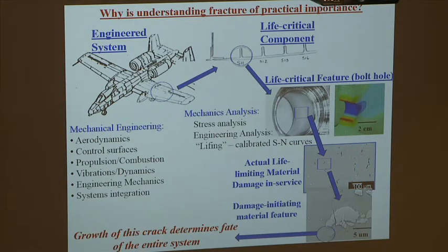And if you really zoom in and see what these cracks look like, they tend to initiate at small particles and grow out, and then they link together, and eventually a big one becomes a fracture. But it's this process, and ultimately what's happening at the tips of the crack here, that determines the fate of the entire airplane. So we can do engineering design above this level, but ultimately it's a material